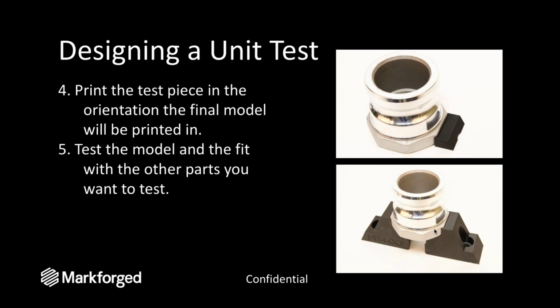So unit tests can be really, really valuable because of this, especially when you're working with fiber reinforced parts that can end up being a little bit more expensive. The parts themselves could take a day to print, and you can print out this 15-minute part that ensures that that day-long print is going to succeed, and it only takes about 15 more minutes of design time. So instead of printing a day-long part, realizing that the part itself is not going to work out, and then having to reprint that entire part, that's 2 days of printing, whereas you could save half of that by just printing a small test to begin with.